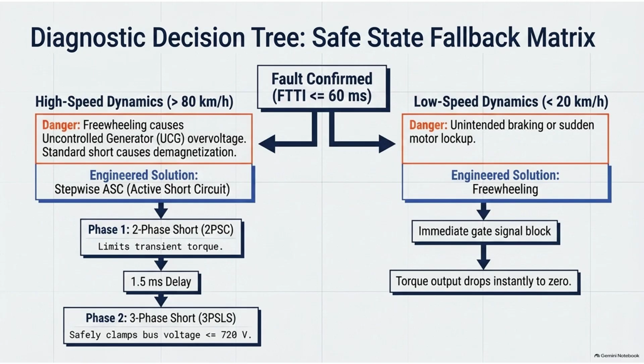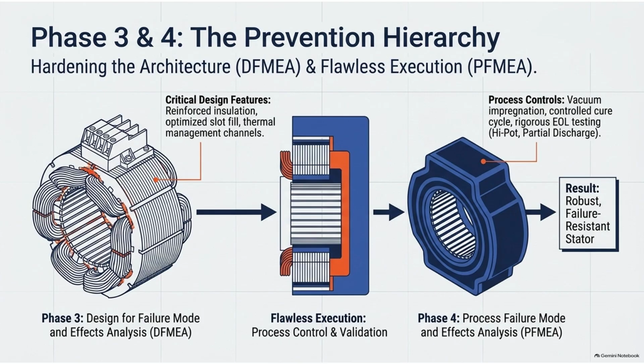Why exactly 1.5 milliseconds? What is physically happening inside the motor during that delay? That precise 1.5 millisecond window allows the asymmetrical transient DC component of the short circuit current, governed by that armature time constant formula we just discussed, to naturally decay through the stator resistance. It is mathematically calculated to let the peak demagnetization current and the maximum torque spike pass harmlessly. It's letting the kinetic energy of the fault burn itself out.